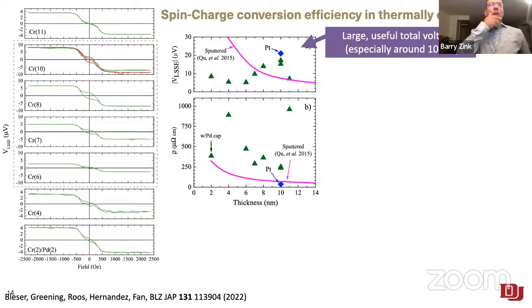So now if we look at this as a function of the thickness in the film, you see something that we were not really expecting. In the sputtered cases that were already published in the literature, you saw a 1/T dependence of the signal, where T is the thickness of the film, which is basically what you expect, since the resistance is just dropping because of size effects. And so you're getting more shunting for thicker films, and it's all rather expected. We didn't see that at all.